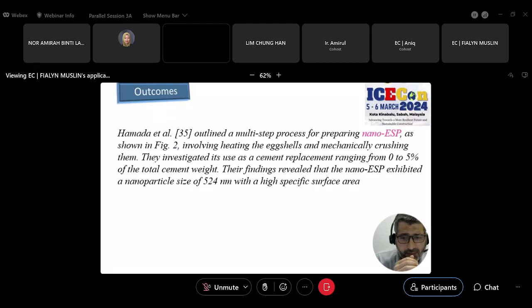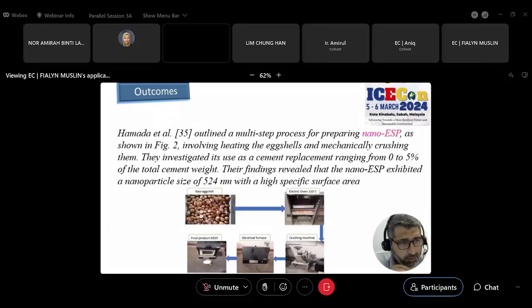So Hamada outlined a multi-step process for preparing nano eggshell powder, as shown in figure 2 here. They outlined a multi-step process for preparing nano ESP, eggshell powder, involving heating the eggshells and mechanically crushing them. So as you can see here, heating in an oven up to 110, then mechanically crushing it. Then they investigated its use as a cement replacement, ranging from 0 to 5% of the total cement weight. Their finding revealed that the nano ESP exhibited a nanoparticle size of up to 524 nanometers with a high specific surface area.